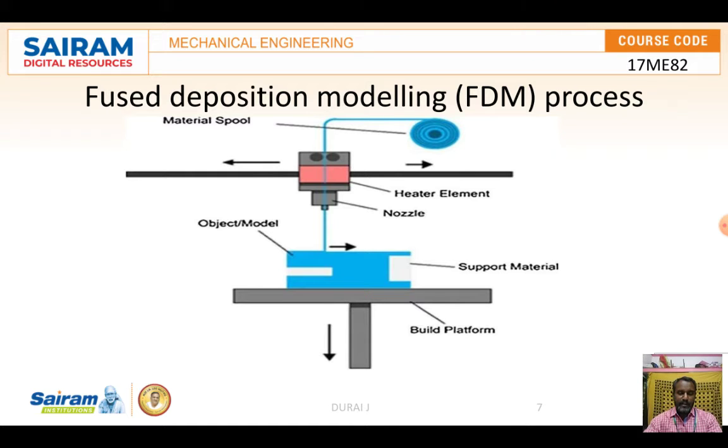Any necessary support structures are automatically detected and generated. The slice thickness can be set manually anywhere between 0.132 and 0.356 mm. Converted into inches, that is 0.0052 to 0.014 inch. It depends upon the model needed.